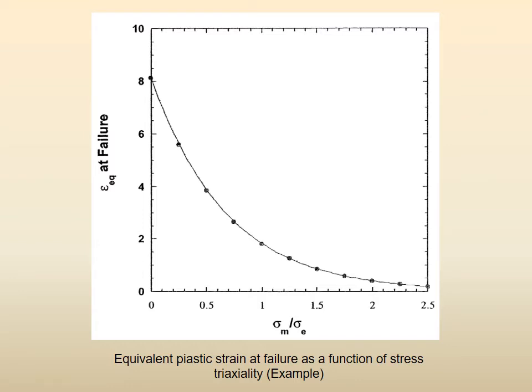So this is the plot that you will get. This is the actual plot of that equation. But I am just interested for you to get a rough idea. So on the vertical axis, right, equivalent strain at failure. On the horizontal axis, the ratio of mean stress to equivalent stress, right? So this is, my typing mistake, equivalent plastic strain at failure as a function of stress triaxiality. So at 0, this is a very large strain, right? And as you increase the mean stress, compared to the equivalent stress, then it keeps on going down, and these are the values. So this will happen as the mean stress increases in comparison with equivalent stress.